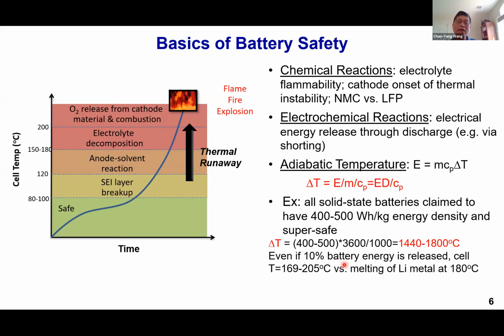Even if only 10% of the energy is released, we will see the cell temperature rise between 170 to 200 degrees Celsius, and that's already causing the melting of lithium metal on the anode side. So now you have solid electrolyte, but a liquid anode material, which will cause internal shorting with the cathode everywhere. So it's a very messy thing.